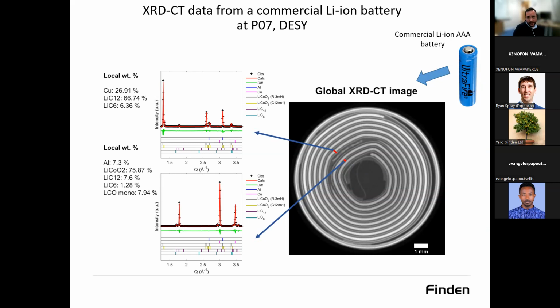So they are very rich in chemistry, especially when it comes to real devices. For example, here we're looking at an XRD-CT image that comes from a AAA lithium-ion battery. And when we look at the diffraction pattern from a voxel that comes from the positive electrode, it has very different characteristics when we look at the corresponding one from the negative electrode.